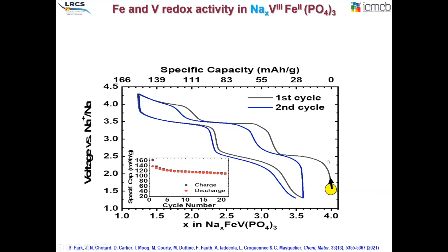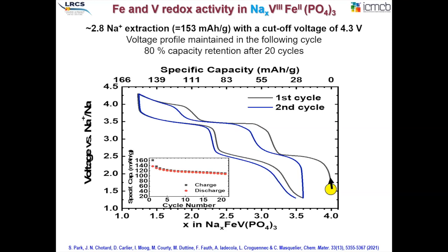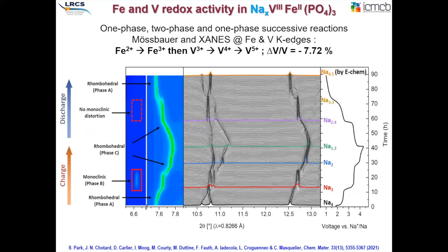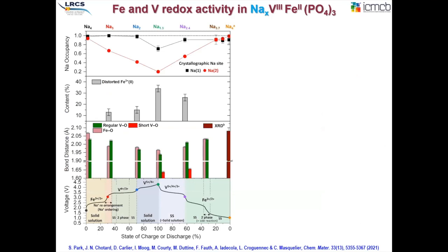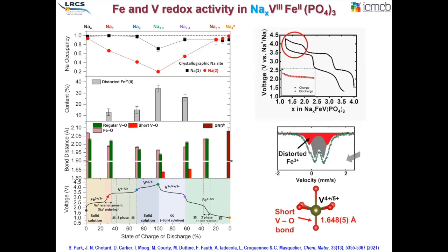It shows three extraction phenomena up to 4.3 volts versus sodium, with the progressive oxidation of the vanadium and iron. And you can see that basically the phenomenon is not completely reversible, as we have only two phenomena in the subsequent discharge. This shows a rather high structural stability over cycling, with many intermediate phases occurring upon sodium extraction and insertion. And we were able, thanks to X-ray absorption spectroscopy, thanks to Mossbauer spectroscopy, to fully determine the mechanism of sodium extraction from these compounds.